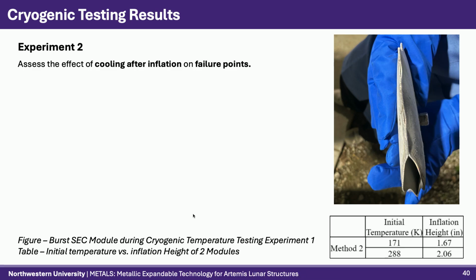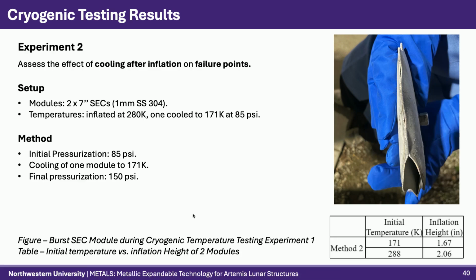For our second experiment, 2 inflatables were pre-inflated to 85 psi at room temperature before one was cryogenically cooled. Both were then inflated to 150 psi to test if temperature affected inflatable failure. Our results showed that cryogenic pre-inflated inflatables resisted changes in volume, but showed no change in burst pressure.